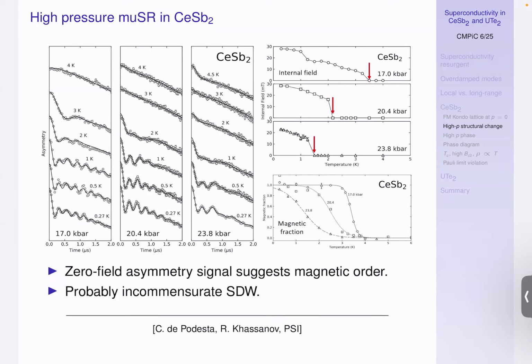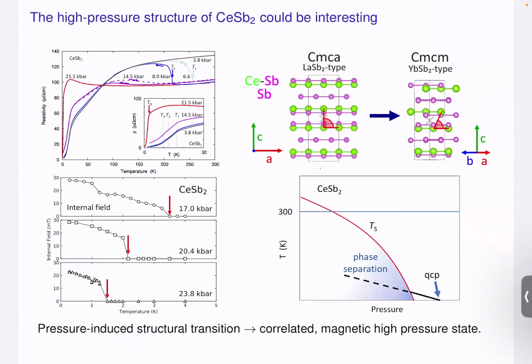We think it's an incommensurate spin density wave order. So this is now the situation. We have a structural transition, the red line, which comes down as a function of pressure. You can cross it in X-ray diffraction at high temperatures, and you see the transition here, or you can cross it at constant pressure as a function of temperature, and then you see these jumps in the resistivity that we saw. And then at high pressure, you have a magnetic transition. This magnetic transition extrapolates to 0 somewhere, and that should be a quantum critical point. So that's where we should look.